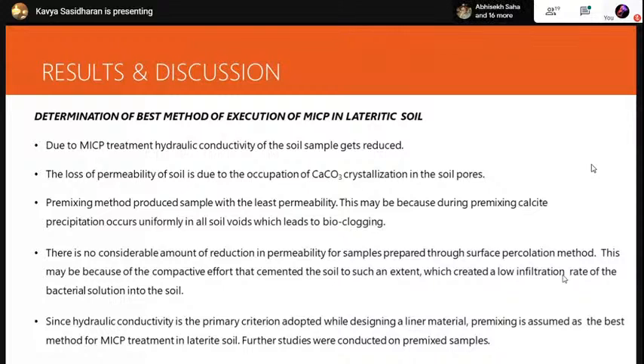And in the case of samples prepared through the surface percolation method, what I found is that there was not much reduction in permeability. This may be because of the compactive effort that cemented the soil to such an extent that it created a low infiltration rate of the bacterial solution into the soil. So the hydraulic conductivity is the primary criterion adopted in the design of a liner material, and hence premixing is assumed as the best method of MICP treatment in lateritic soil.